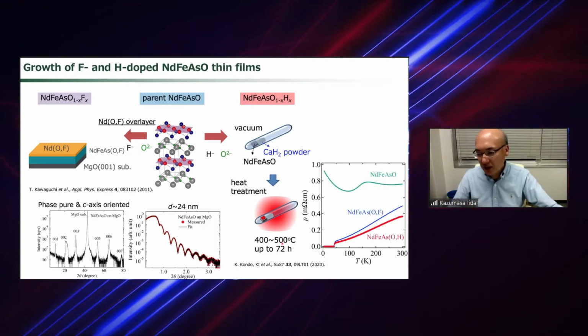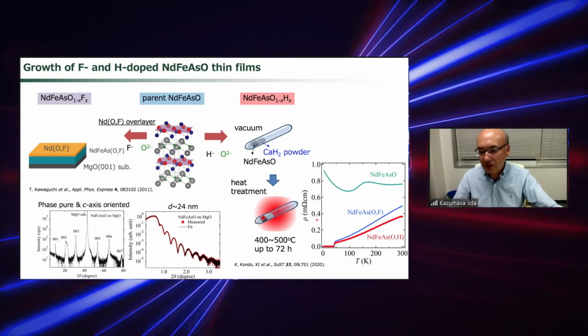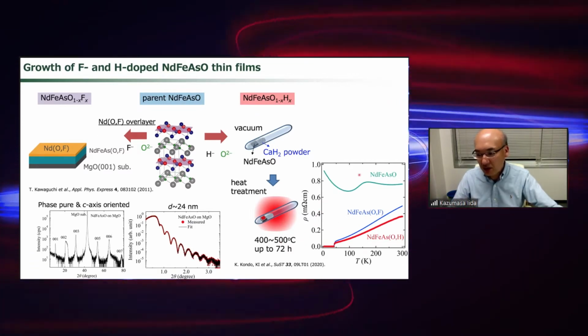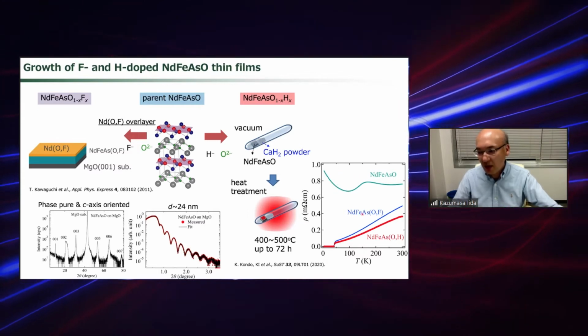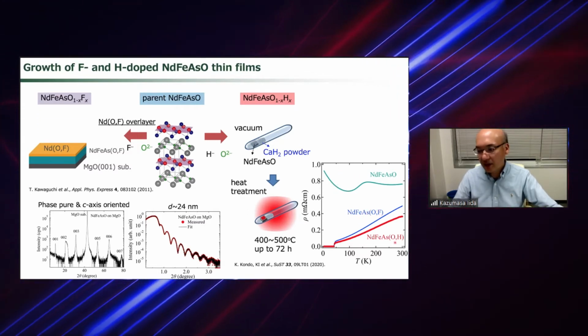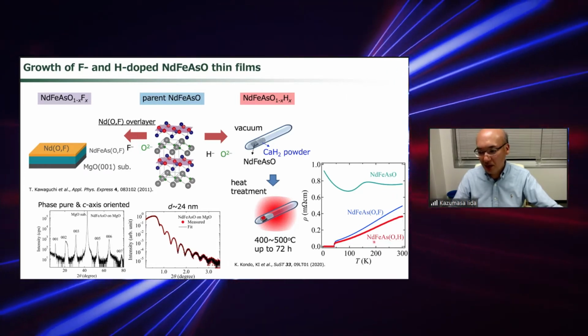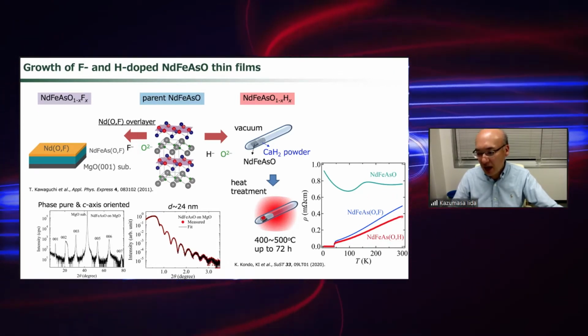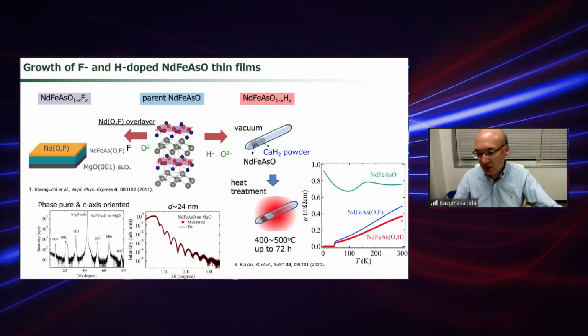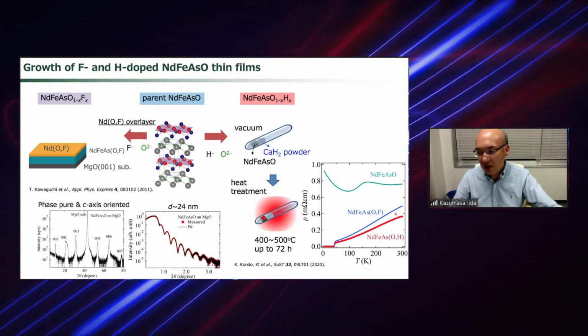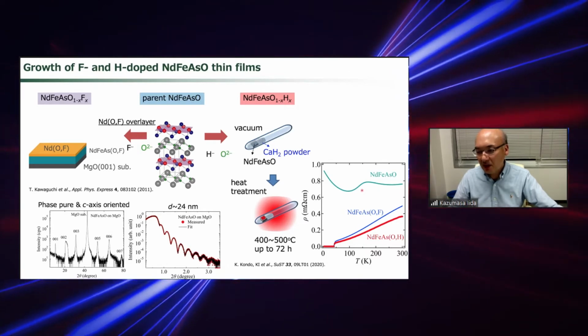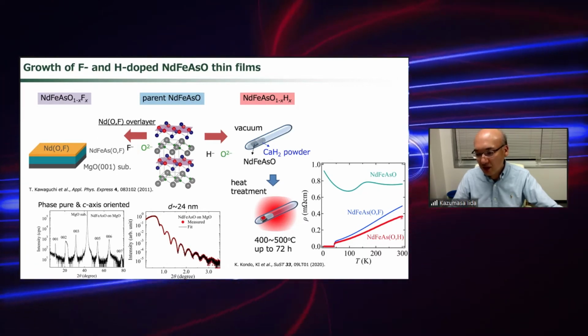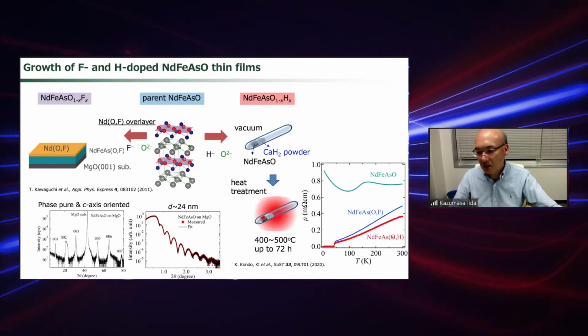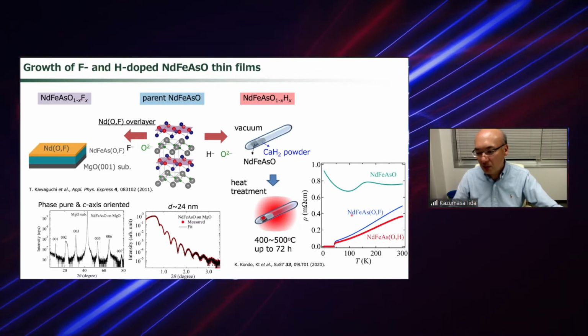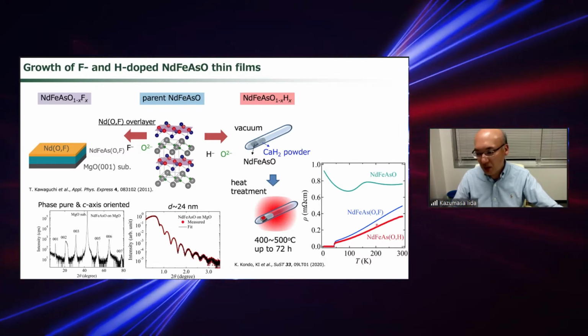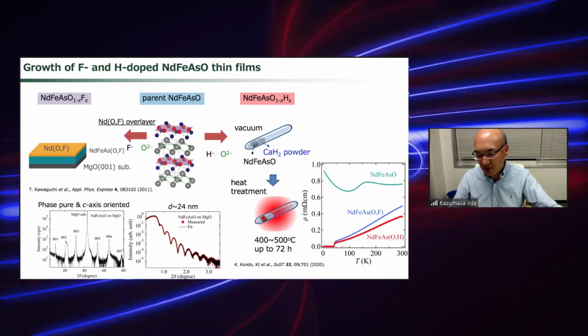And this is a summary of the resistivity curves of the parent neodymium 1111 films, as well as the fluorine and hydrogen-doped 1111 films. As I mentioned before, in the hydrogen doping case we obtained the overdoped state. That is the reason the resistivity in the normal state is the smallest for this hydrogen-doped sample. Both the hydrogen and fluorine-doped samples show a TC around 50 Kelvin.